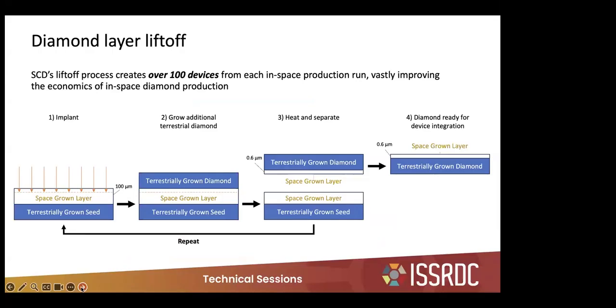A critical aspect of our production process is our ability to produce many devices from each diamond grown in space. After the diamond is returned to our terrestrial labs, we can use a liftoff process illustrated here to selectively remove active layers of high-quality space-grown diamond around 0.6 microns in thickness for use in devices. Because the diamonds grown in space coming back to our labs will be about 100 microns or greater in thickness, it means that we can make more than 100 devices from each of the in-space diamonds we grow. This is critical to achieving high returns on our in-space production activities.